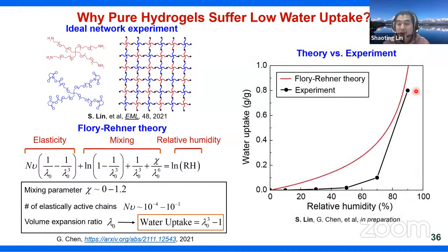The black dots are the measured data, and the red curve is the theoretical curve. We can see that at a high humidity level, the theory really agrees with the experimental result, which is typical in the domain of swelling. Many people have been studying that domain. However, at a low humidity level or a medium humidity level, the experimental result is much lower than the theoretical prediction. So what is the reason?